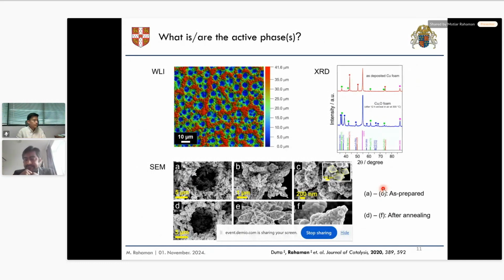So our question in this project was, if we directly use a copper oxide material for carbon dioxide conversion, is there any possibility that the oxide survives under this electrochemical condition, or does the oxide first get reduced into metallic copper and then work as an oxide derived catalyst? To do that, we did some operando spectroscopy measurements. Here, this is as prepared dendritic copper, and then we oxidized the dendrite and made some copper +2 and copper +1 oxide on the surface.